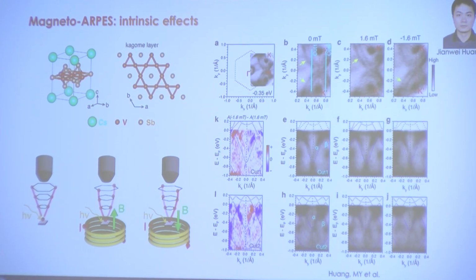If you stare at this long enough, you'll notice that under zero field, the bands at the K point and the K prime are very similar. If you apply even 1 millitesla, what you see is that these remain sharp, and these are broadened, disappearing. If you flip the field, you see that these remain sharp, and these are broadened. So there's some effect which is odd in field.